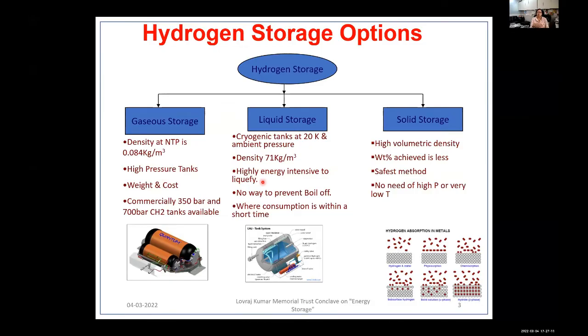And at the same time, these require super insulated vessels, and whatever good insulation we may use, there will be losses involved. So there are boil-off losses. And at times, even if you have a full tank and you leave it for a few days, you will find it vacant because of these boil-off losses. So this can be particularly useful when you want to use it in a short duration. You want to use it after refilling.